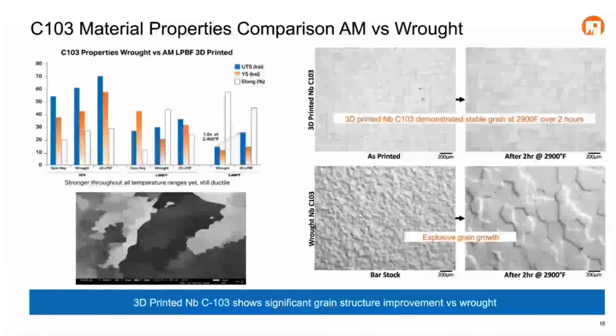So getting into why this material benefits from the additive manufacturing process, and why we can actually beat the wrought form of this material, it really comes down to the printing process. We'll talk first about the microstructure. So again, laser powder bed fusion, we're talking over 1 meter a second of laser travel speed, and temperature gradients, or cooling rate, that can be in the 10,000 degree per second realm.